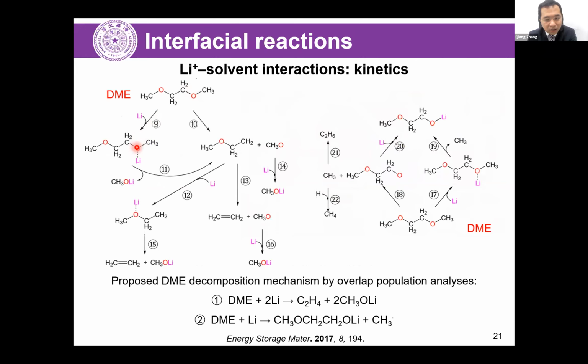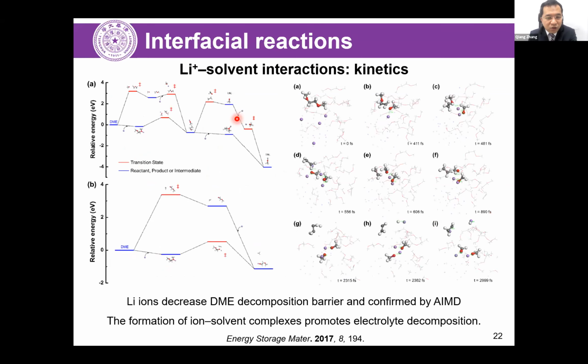It's found that the decomposition of the organic solvents was quite easy. And this step was with quite a low energy barrier. And then the lithium ion prefers to attack another oxygen. And once the electron reaches that site, then ethylene gas can be released in the electrochemical system while a lot of solid products can be deposited on the surface. In contrast to the lithium-ion solvent complex routes, the direct decomposition was always with a high energy barrier. So in fact, we try to compare the energy barrier with the lithium-ion solvents and the direct decomposition. And we found that the ion-solvent complex provides a quite easy and facile route to help the electrolyte decomposition.